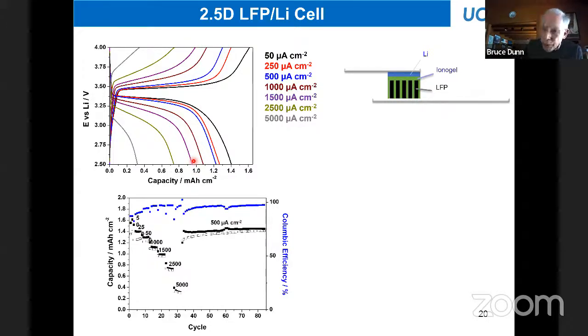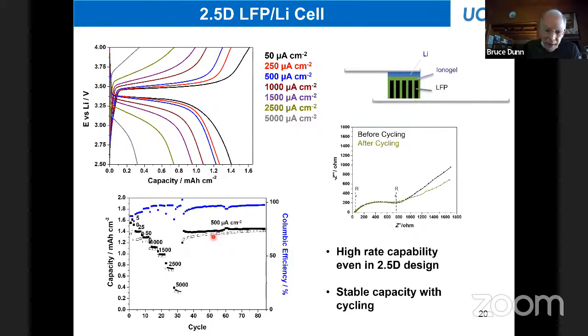So now, of course, we know very well how to design the material so that we can increase the areal capacity accordingly. But this is the real benefit of the 2.5D battery. The fabrication is a lot easier, as you can see, and also the performance is very good. This just shows you the capacity of the system over the cyclability of the system. We've gone a couple hundred cycles and it holds on to its capacity quite well. And then finally, the other part has to do with the impedance, still a little high because of the nature of the electrode. However, we have no change in the electrode impedance over time, or the cell impedance over time. And that part is really good.